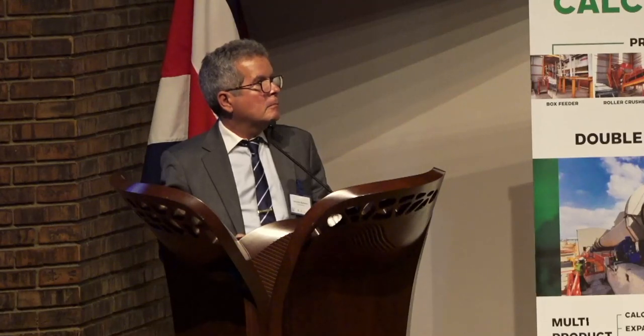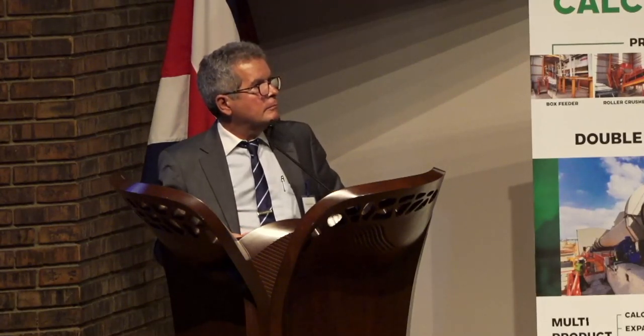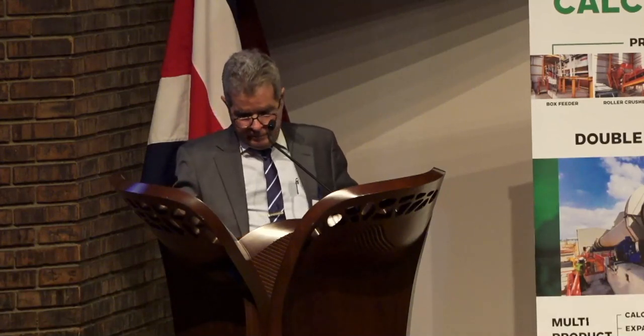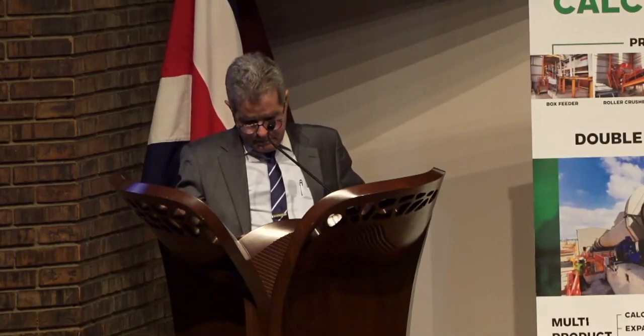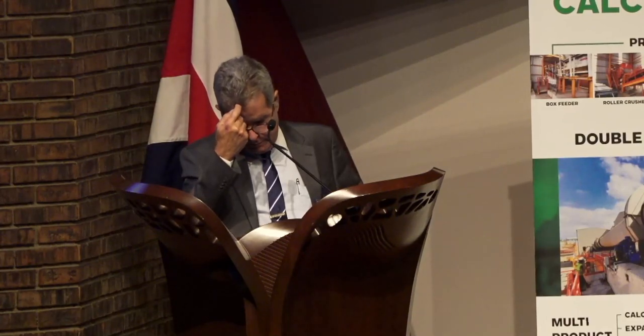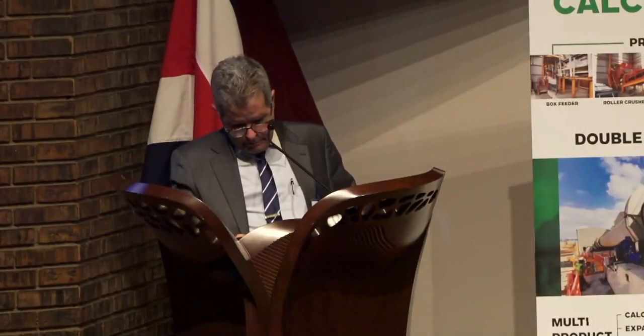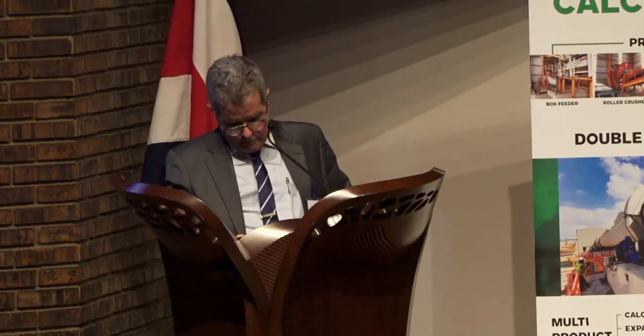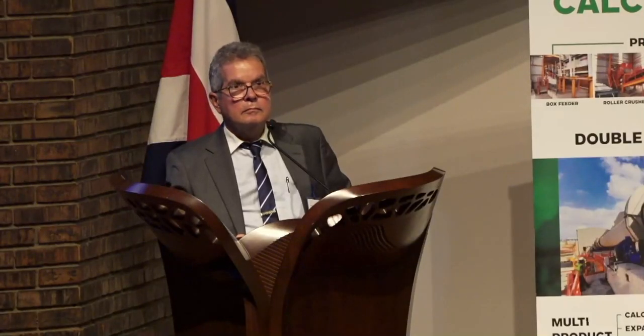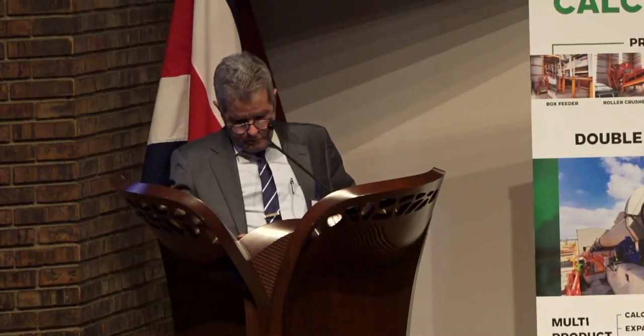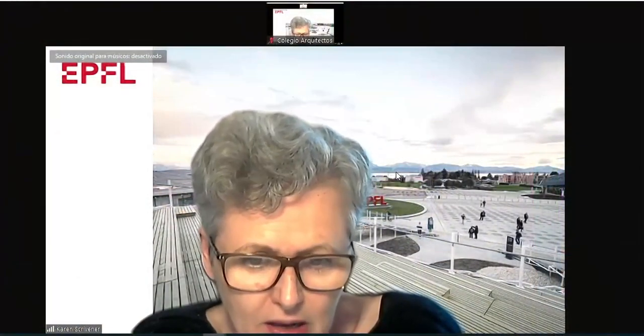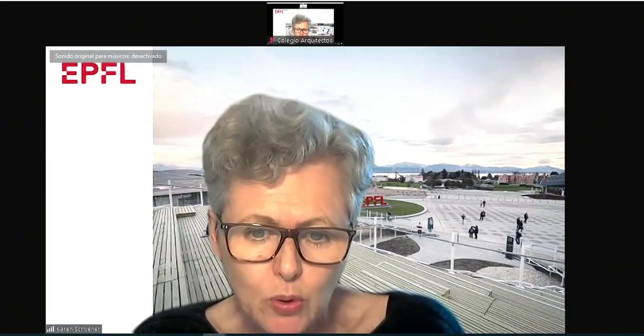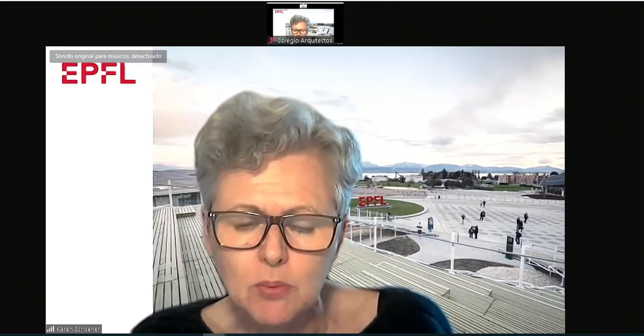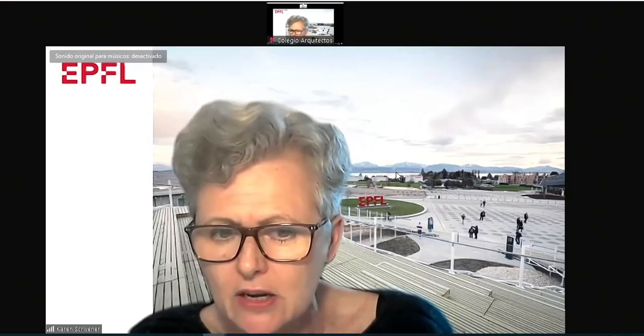Well, basically they compare extremely well. Calcined clay is much more reactive than either of these. So, I should have included this slide, but we have a comparison with different mixtures, and in the long term, they all have about the same strength, but the strength of the LC3 systems is developed much more quickly. So as I showed, you could even have the same strength at 1 day as a Portland cement reference, which you certainly can't do with either of these other materials.